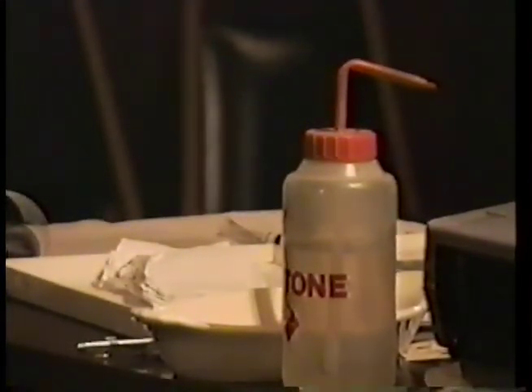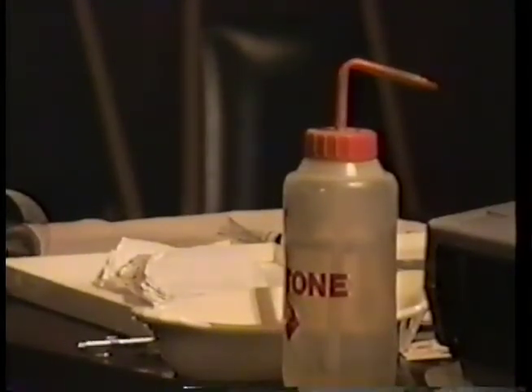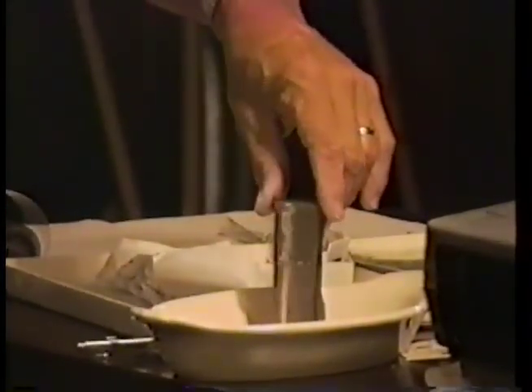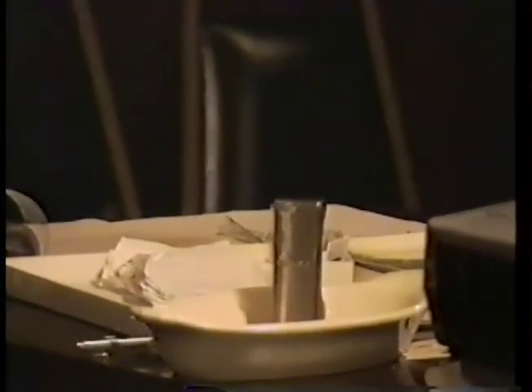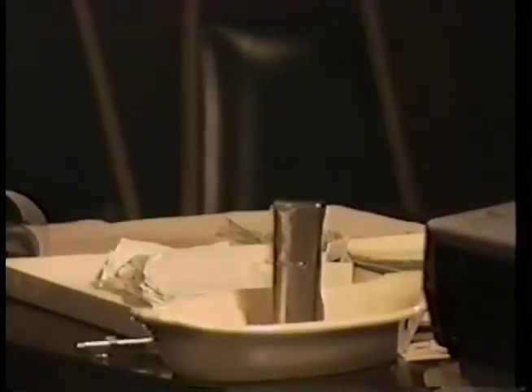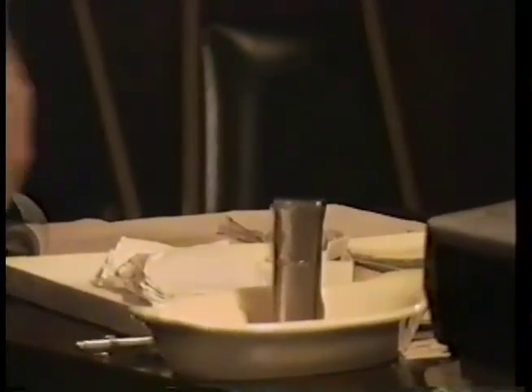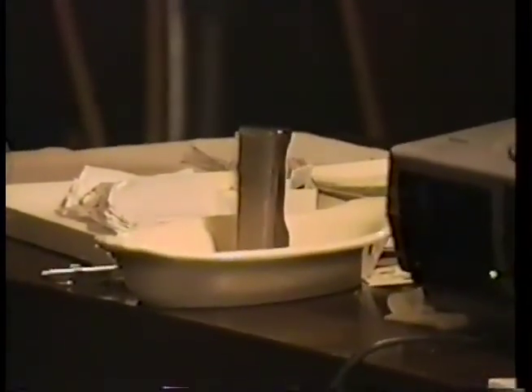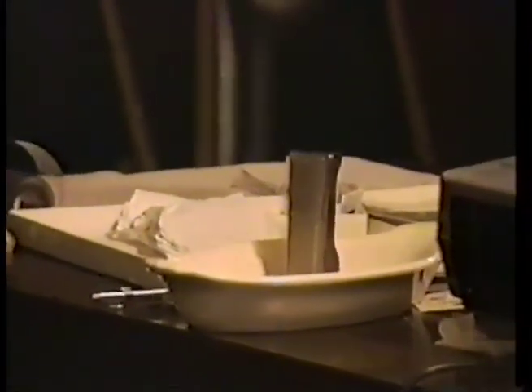When you're working on a large liner, you can get both hands involved, and you can just lightly rub it while you're flushing it with the solution, otherwise it'll get real sticky and you'll get your finger on it. I have instructions on how to do this in writing, and I'll leave those with anybody. But what I recommend you do is, when you first get a cylinder back from being reconditioned, take some fax films off the head end, below the ring reversal area, and down in the skirt end.